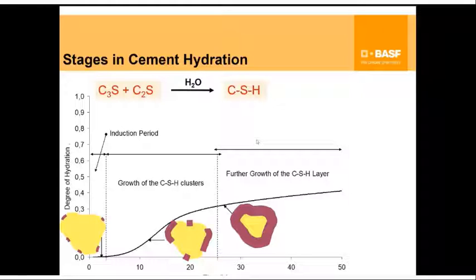Now, while this looks sort of interesting, this is also sort of bad in one way, right? Because you cover all of the cement surface pretty early in its hydration reaction. It makes it more difficult for water to enter through the purple CSH surface to get to the yellow cement particles, to hydrate, to dissolve, and bring it back out and precipitate as CSH. So this is why it takes a long time for the concrete to gain its full strength, because the rate of cement hydration starts to slow down quite significantly.